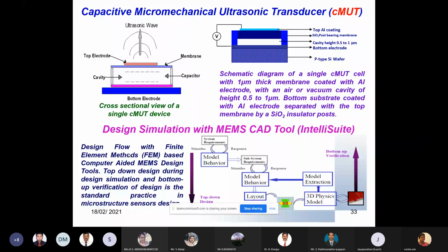Here, simply, the right hand side shows a simple structure. Bottom surface, air cavity, and the light blue color is the insulating pillar. The top one is a membrane. The light blue color is an aluminum coating on the membrane for electrical contact. In the same way, the bottom also has an aluminum coating. Between these two electrodes, you can measure the capacitance. Suppose you apply a DC potential between these two electrodes, what will happen?